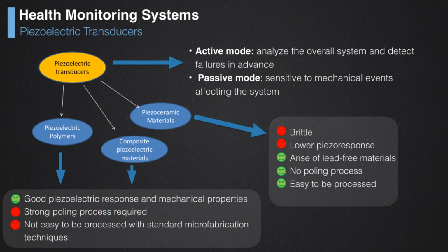Other solutions are the piezoelectric polymers. They are flexible, so this is an extremely good point for the application in the case of health monitoring of fuel tanks, of conformable devices. But they still require a poling process. What does it mean? It means that before using the sensor, you have to apply an extremely high electric field and align all the dipoles, the ferroelectric dipoles in the material. This is to obtain a good remanence state, after which you are able to apply a pressure and read easily a charge on the material.